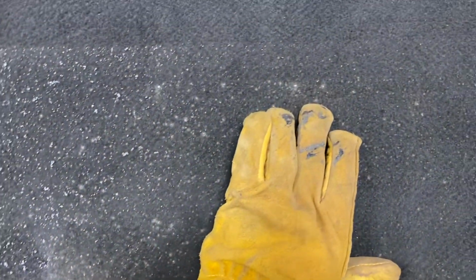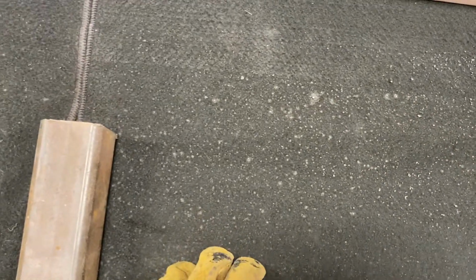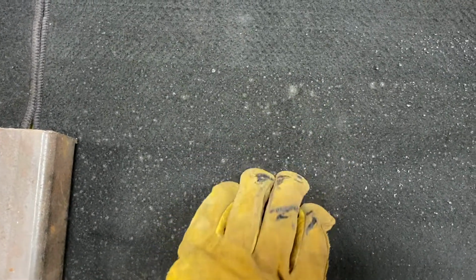So here's on the standard side. You can see, oh, we got some spots there, some over here, some right there, where it really melts in. You know, it's just not dense, so it doesn't hold it back. So here's the 3 layer, and even here we got a big old piece of slag. It just doesn't melt in as much as the standard one. You know, because of how dense it is, it can just absorb that heat.